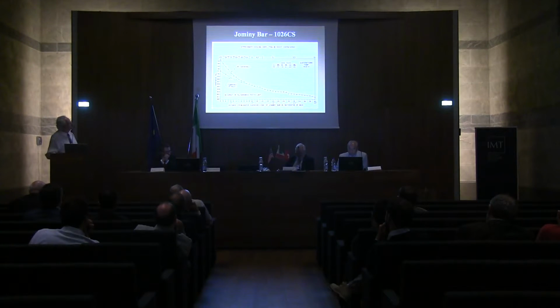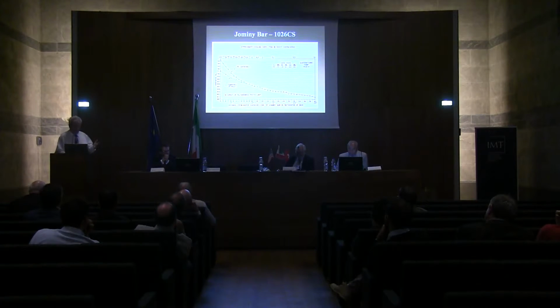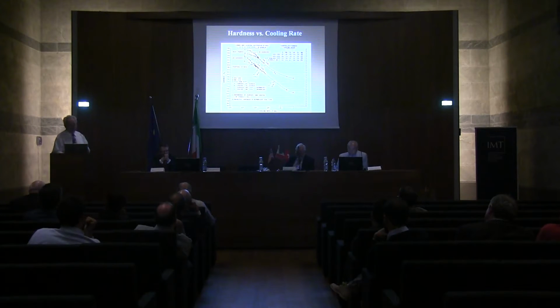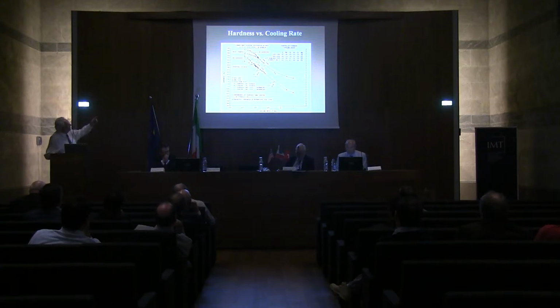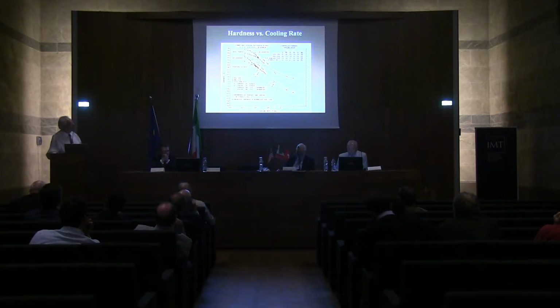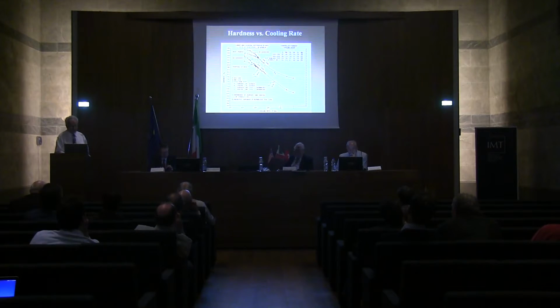And here's the same data for the 1026 carbon steel Jominy bar as comparison. Of course, it's lower carbon, so you can have somewhat lower hardness. Here we're plotting the hardness versus cooling rate for the 1026 and the 1035 steel on the same curve, and you can see surface and center values. The air-cooled values are in the lower part, just below the center, slightly to the right, where it says AC for air-cooled. C and D are the kind of hardnesses that we actually got on the air-cooled samples, so you can pick off the cooling rates. Whereas up at the top, where you have the EB and the green arrows, that relates to the oil quench data, and A and B are also oil quench data. So there's a big difference in hardness.